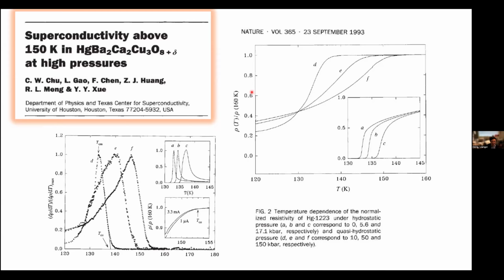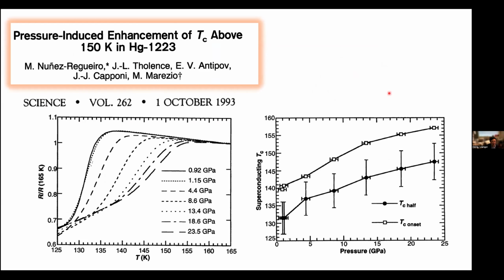And indeed it is. They pushed the TC above 150 Kelvin back in 1993. The curves under pressure at that time were not that sharp, but at least it gives a very nice indication that onset TC is above 150 Kelvin. And the same year, another group, I think from France, saw pretty much the same onset TC going up above 150 Kelvin, and it's very exciting. So that's the record at that time.